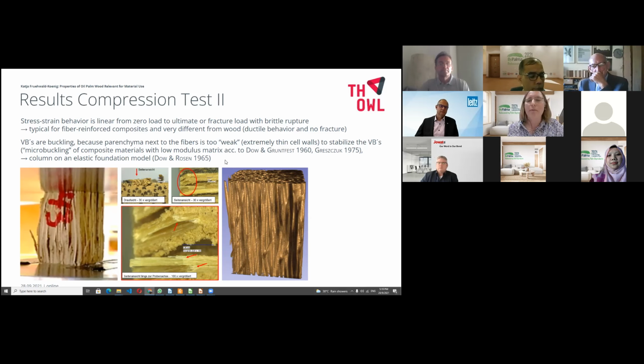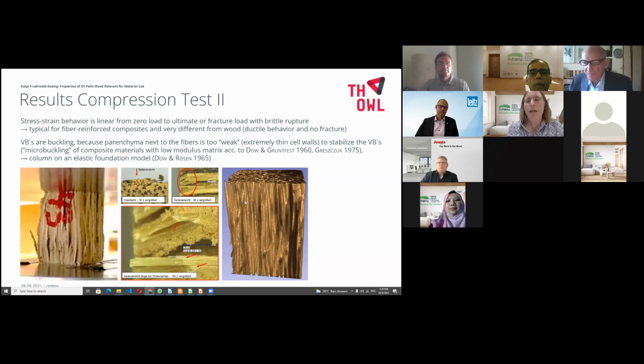This is in line with the literature for composite materials, matrix modulus. In addition to fiber buckling being caused by mechanical compressive loads, fiber buckling might be caused as well by shrinkage stresses developed during drying, which result from the matrix having a different coefficient of expansion than the fibers.